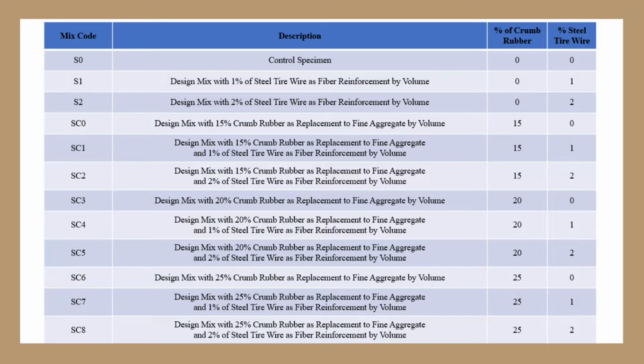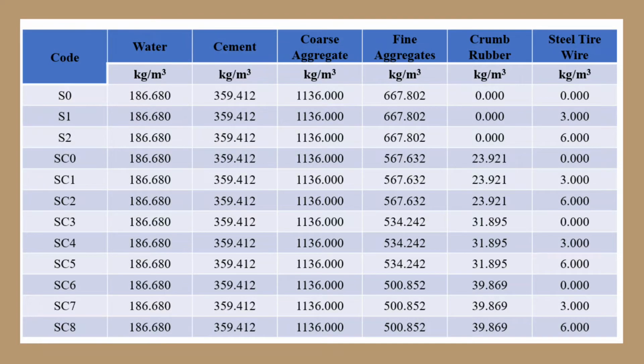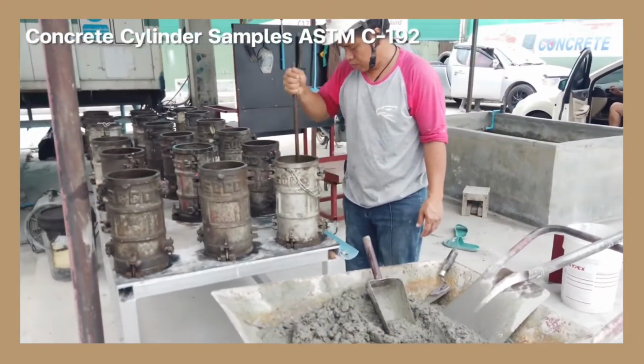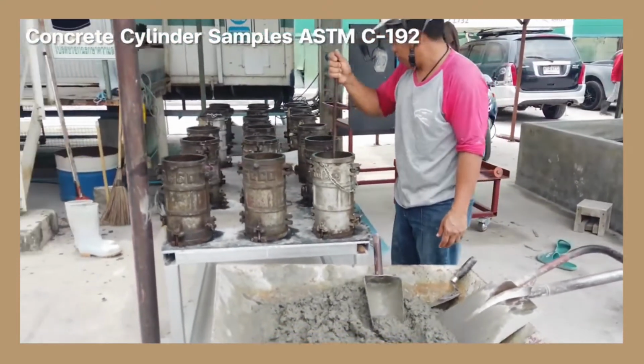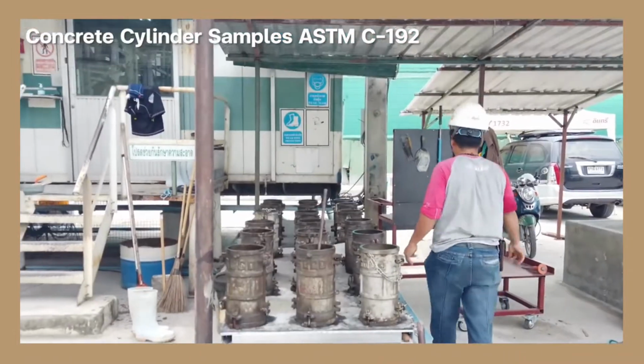The control specimen will have 0 steel tire wires and 0 crumb rubber. Design mixes with 1 and 2% steel tire wires will be denoted as S1 and S2, respectively, while variation in the design mix with the integration of steel tire wires and crumb rubber will be denoted as SC0 to SC8, respectively. Concrete specimens will then be left to harden for a day before being cured in accordance to ASTM C192.